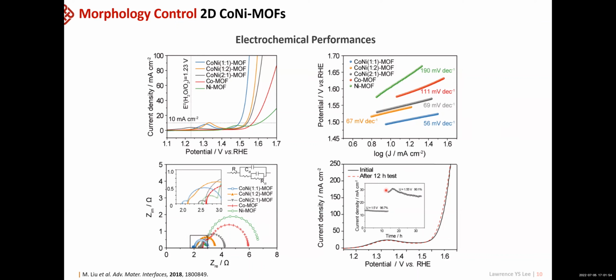When we did the stability test, less than 10% decline after 30 hours was recorded, which is not too bad, but this raised a question about its stability. That's why we studied another set of experiments. If you think about the MOF structure and the catalytic reaction, the active site is either a cobalt or nickel metal node, and in order for them to catalyze the OER reaction, either the substrate or intermediate has to come and interact with this metal node, and that may weaken their initial bonding to the linker molecules.